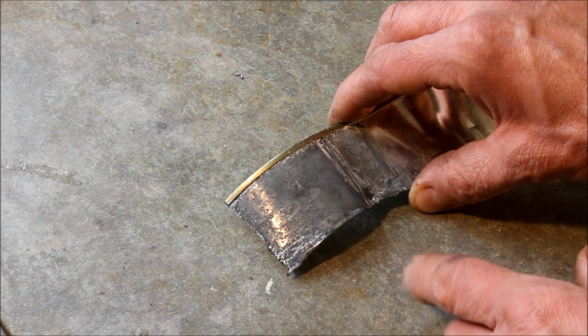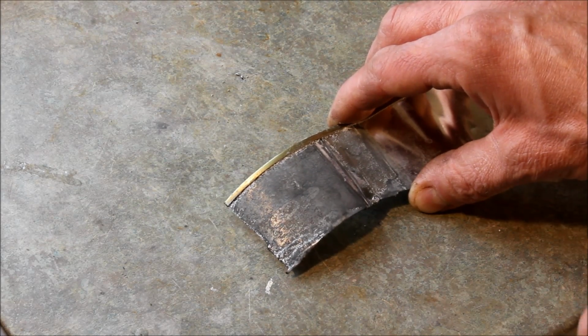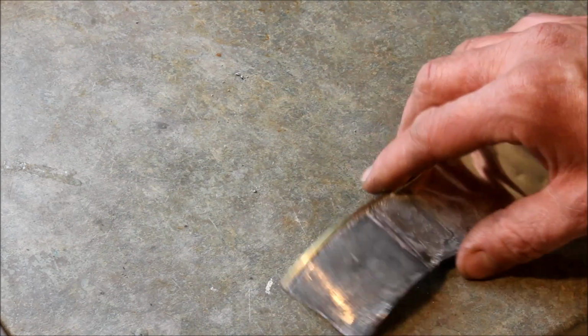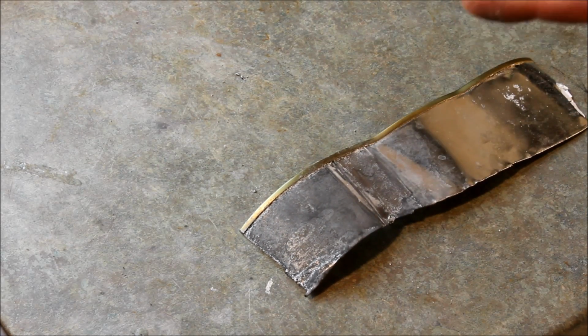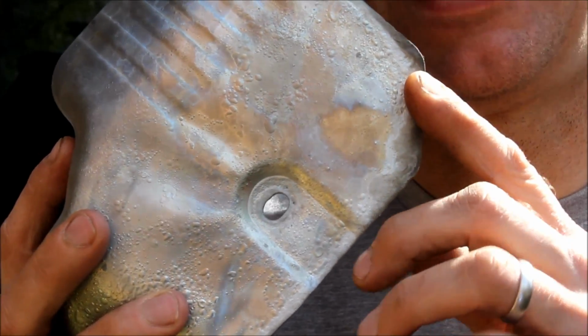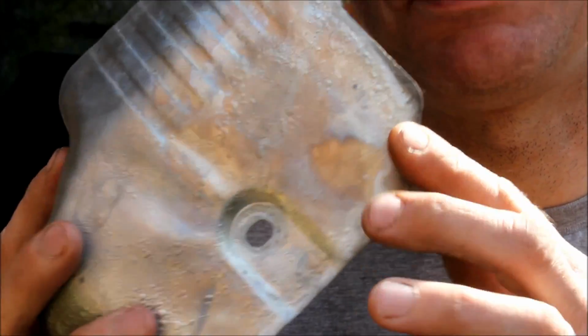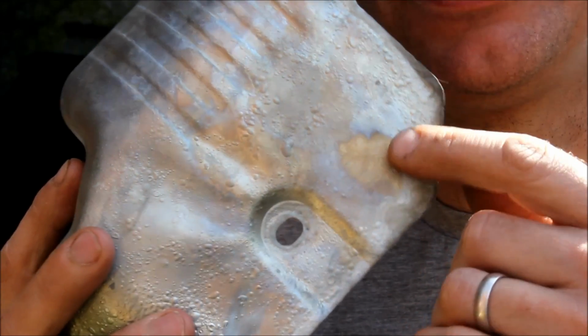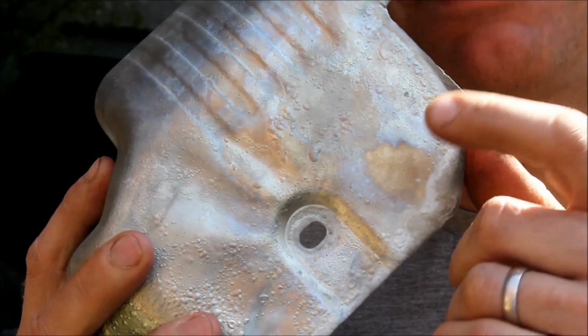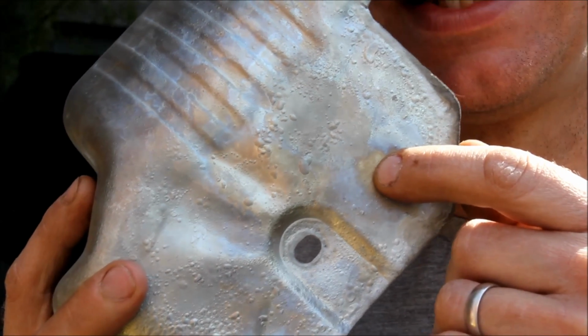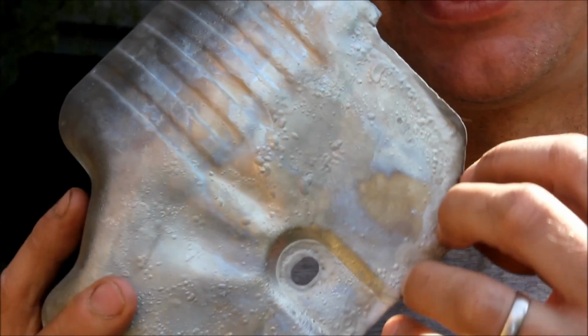If it's localised, you're just getting some parts burning but not others. That's current density. It's just that those parts that are burnt are receiving more than they should, more than their fair share of the current. The bigger problem though is that this seems to be made out of some high carbon, high strength steel. Now that's good because it gives a bit of corrosion protection, but it makes it a right nuisance to try and zinc plate it. The problem is that when we're baking this after plating it, the carbon steel is degassing.